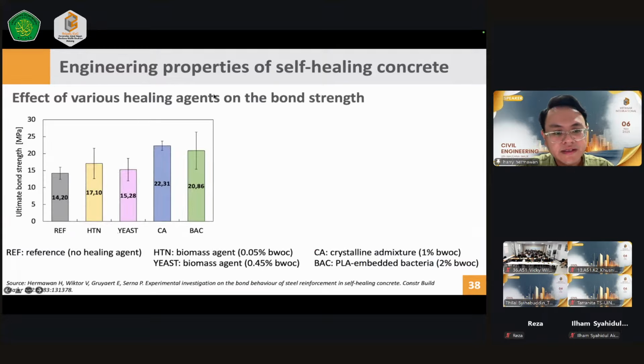So, with regards to the ultimate bond strength, here I also give you some ideas of the effect of various healing agents. If you look here, our normal concrete has an ultimate bond strength of about 14 MPa, and with the addition of the fungi or bacterial biomass, it only increased slightly on the bond strength, although it is not very significant.